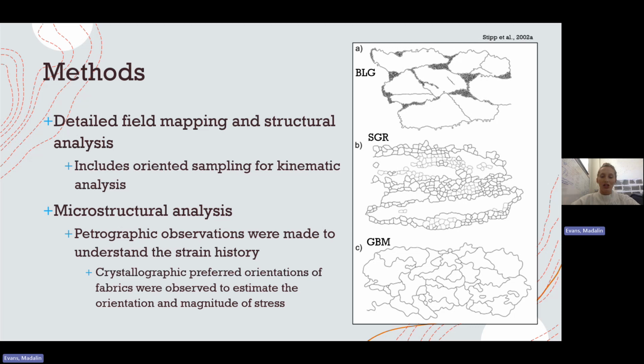So this top one is considered a bulging recrystallization regime that occurs at low temperatures. This has large porphyroclasts with some sutured grain boundaries and some really small recrystallized grains within the other boundaries. Subgrain rotation occurs at moderate temperatures and tends to have these ribbon to polygonized grains and some subgrains within the core and the rim of these relict grains. Grain boundary migration occurs at high temperatures and it essentially recrystallizes the entire rock. This produces these very large and irregularly shaped grains with lobate boundaries.